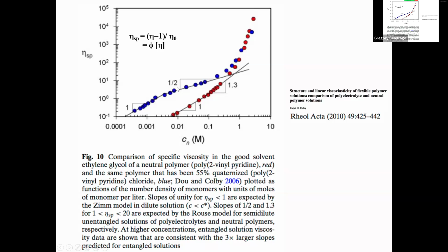But when he has the polyelectrolyte, so he charges it, then he gets quite a bit different behavior. He has the power 1, and then there's overlap of the ion concentration, and finally it becomes linear when he gets to high concentration where the Debye length screens out the charge. So then they just fall on top of each other. It's the same thing once the counter ions from the polymer screen out all the charge effects. So I guess the interesting thing is that they match here, and they don't match down here. So the issue is about polyelectrolyte concentration and how you do this stuff.